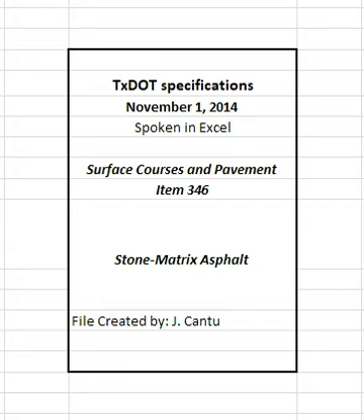The engineer will use the guidelines in Table 10 to determine the compacted lift thickness of each layer when multiple lifts are required. The thickness determined is based on the rate of 110 pounds per square yard for each inch of pavement unless otherwise shown on the plans. Table 10. Compacted lift thickness and required core height. See table in specifications.